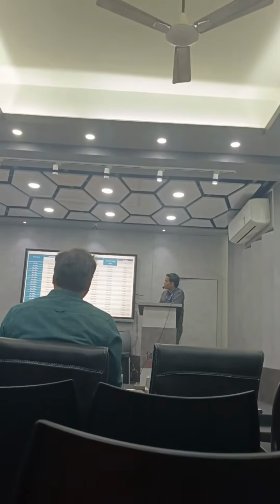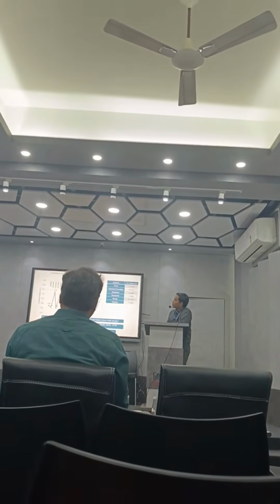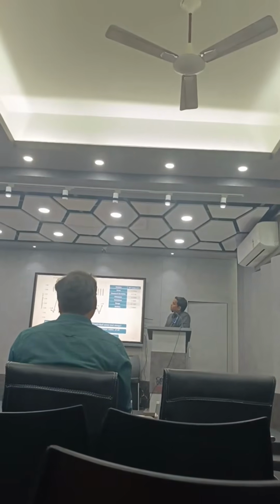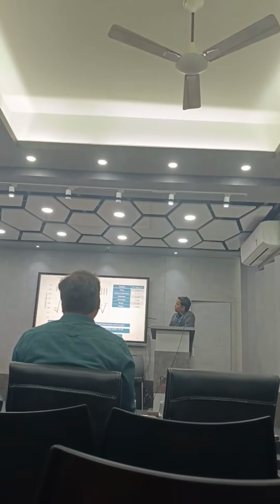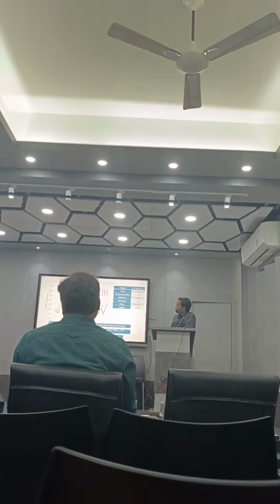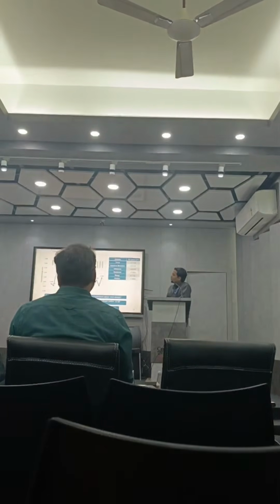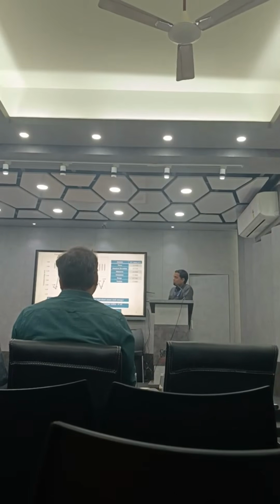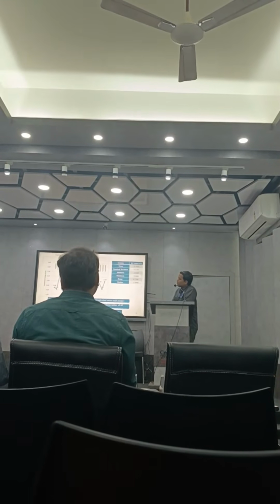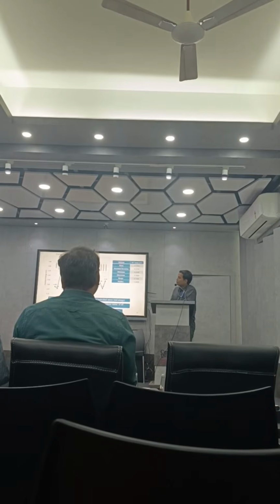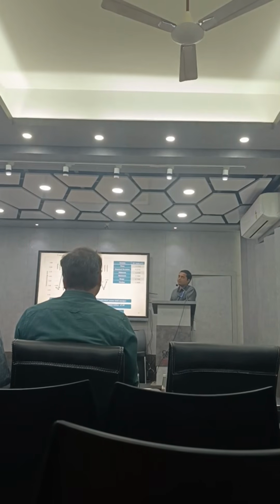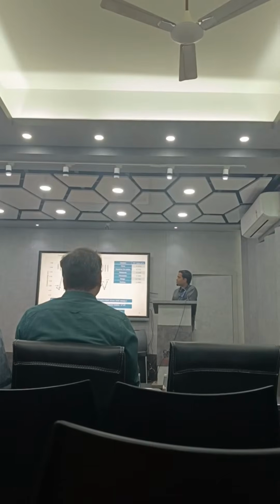Then we calculated the formation energies. This is the tabulation of the formation energy values. The lower part is all about the gallium side, and the above ones are the nitrogen side. The lower the formation energy, the more stable the structure. So doping a transition metal at the gallium side of gallium nitride is preferable.